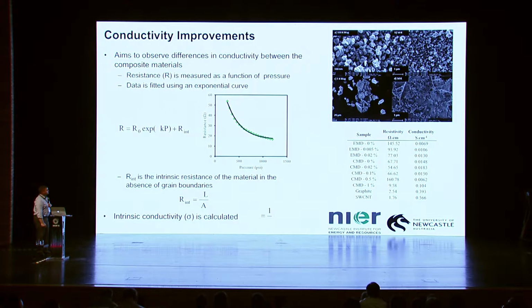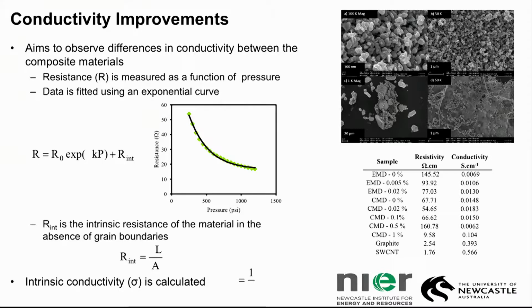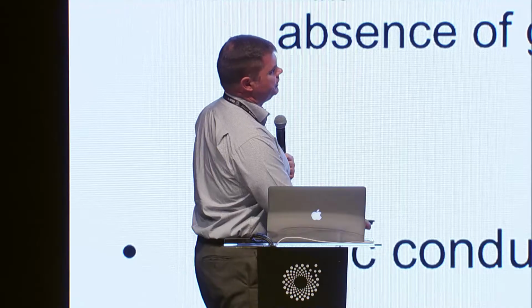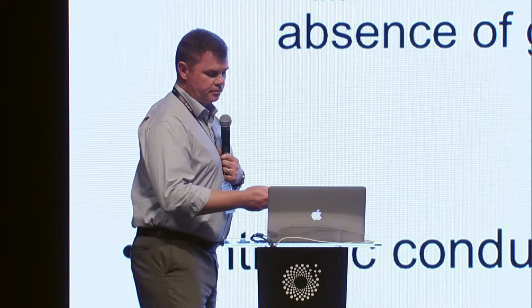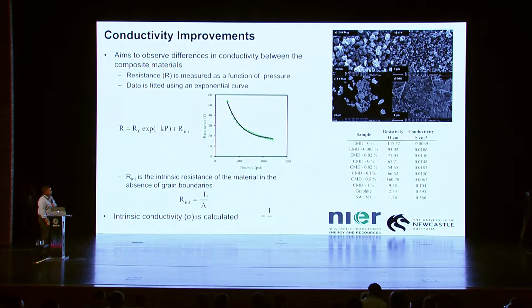How does it go in terms of performance? Well, here we're looking at the conductivity of our materials. Looking at the table over on the right-hand side, we can basically go from about a tenfold increase in conductivity with just a very small fraction of carbon nanotubes included in the manganese dioxide structure. So in that regard, it's quite promising. We're getting a much better mixing of the materials together.